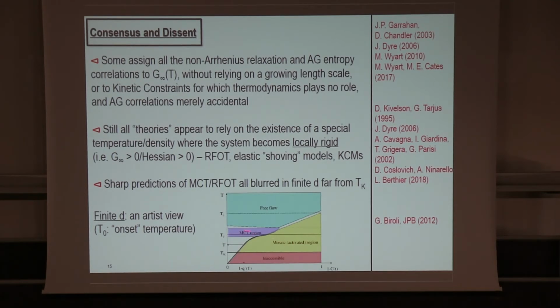And then, it's a small sliver here where MCT phenomenology is going to hold. Above this temperature, one expects free flow, but at long enough times, below some onset temperature, there might be some rare regions that are already activated, and these rare regions are going to be dominant at long times. And of course, this regime here is the regime where the mosaic picture should somehow hold. So because of this, the fact that this region is so small is always going to make it difficult to be sure that the sharp predictions are relevant.